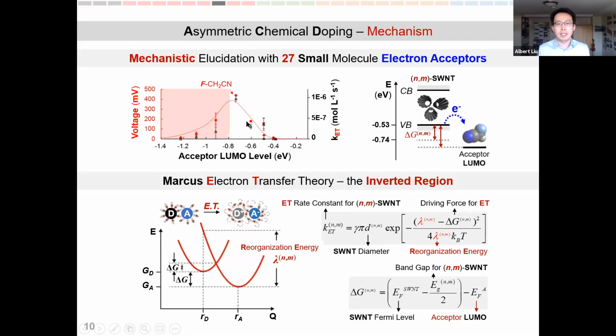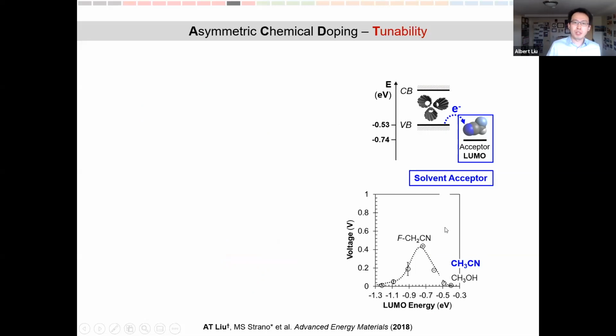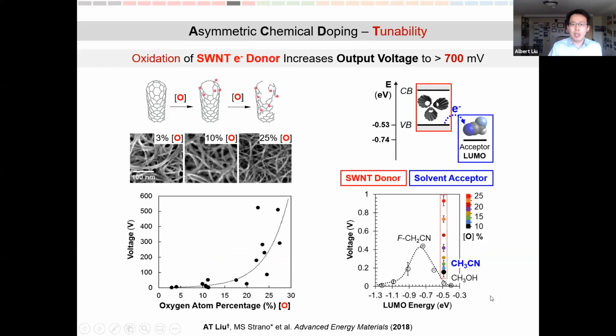Here, what we're saying is basically fluorinated acetonitrile has the perfect LUMO level that gives rise to the perfect driving force that equals the reorganization energy in order for this electron transfer to occur. So this guiding principle of Marcus type electron transfer can explain not only our voltage tunability across all solvents that we have tested, but also it opens up the possibility for us to start tuning our donor substrate.